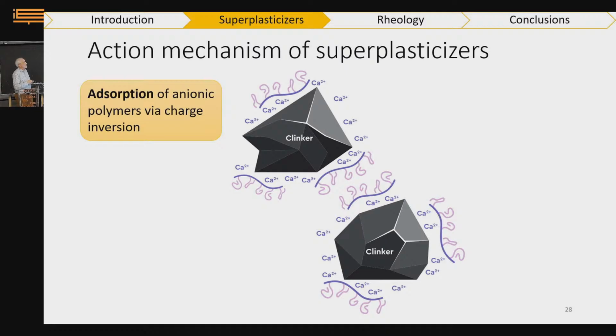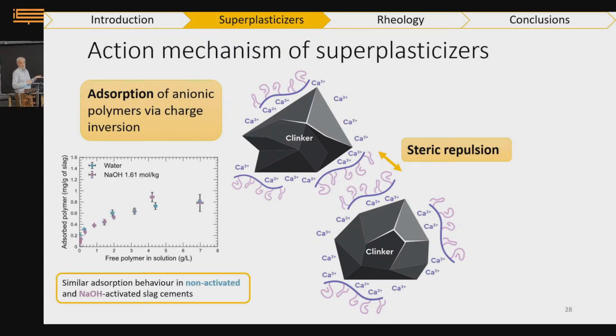So let's go back to how those polymers are working. They adsorb on the solid grain, clinker or slag. Because of their blob conformation, they have a certain geometrical extension in solution, and they therefore induce steric repulsion between the grains. So the first step is adsorption, and the first element is steric repulsion. So why is it not working? Is it because it's not adsorbing? Well, no, it's not. You can measure by different methods, but here it's by total organic content measurements. By difference, you can measure the amount of polymer that's adsorbed from the solution, and you see that the isotherm with sodium hydroxide or without sodium hydroxide is exactly the same. So the presence of sodium hydroxide dissolved in the water doesn't impact the adsorption on the slag. There's some disagreement with that statement in the literature, but here I think it is very clear.